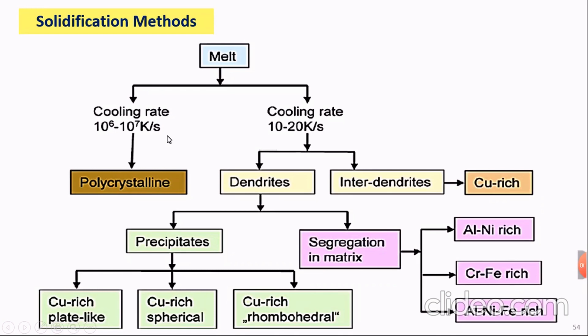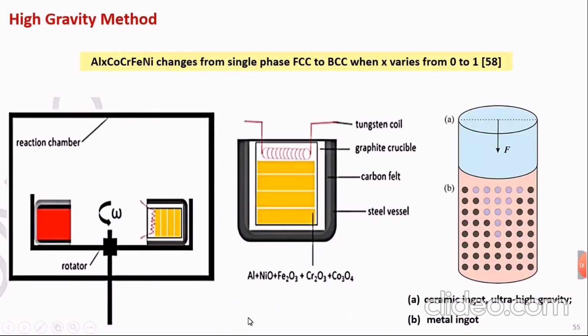For solidification methods, there is a method called the high gravity method. It's not frequently used, but I have to mention it because some people used it in the literature. For example, a group of researchers used aluminum, cobalt, chromium, iron, nickel, and solidified using this method and obtained a single phase FCC, and with aluminum addition it changed to BCC, as we explained previously. In this method, they took the elements and oxides and heated them in a graphite crucible using a tungsten coil, and once melted they applied the rotation or the centrifugal force. Then they have high entropy alloys with graded structure.